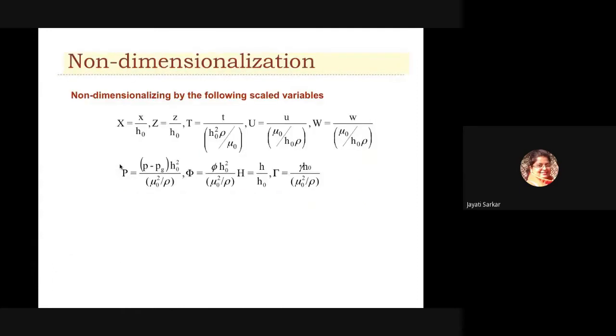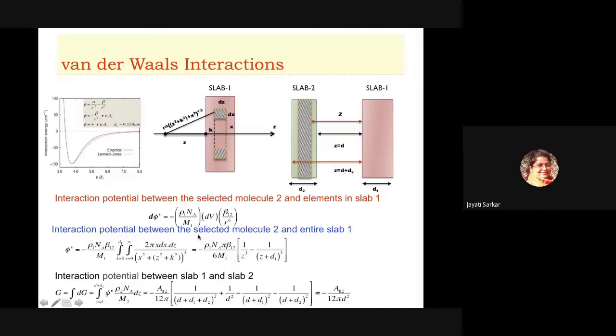So this was the excess interaction potential that was present because of the thickness of the film, as I've told. If it is less than 100 nanometer, you can see that this interaction energy, or the interaction force, which can be the derivative of this interaction energy, is inversely proportional to this gap distance.